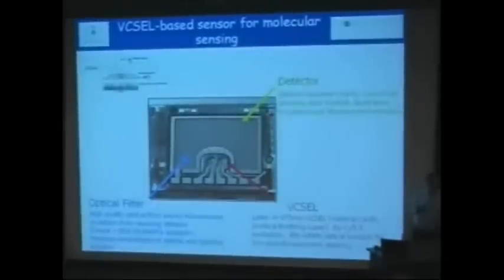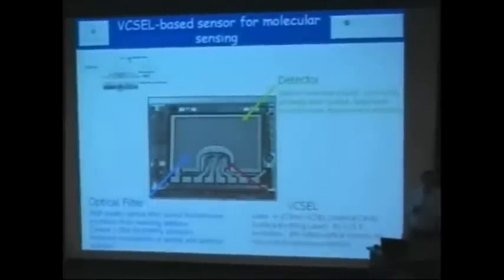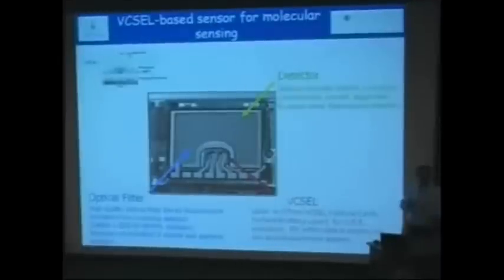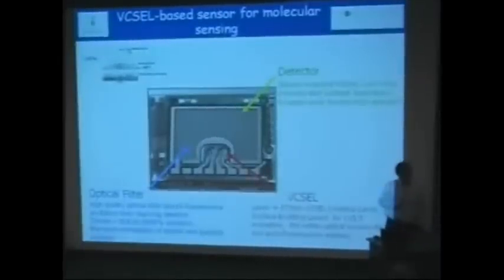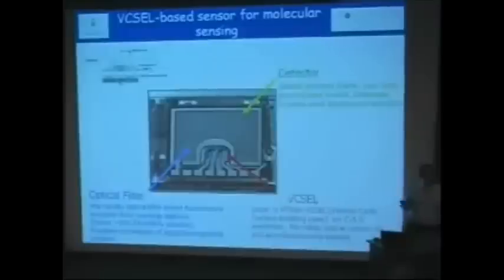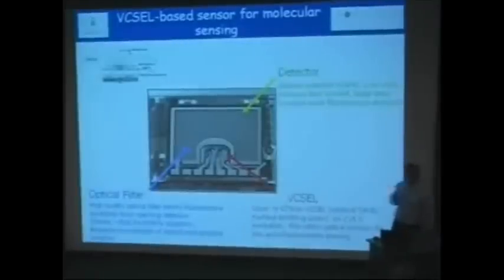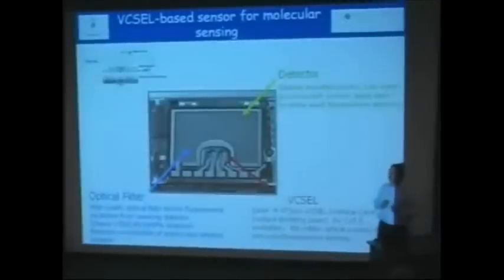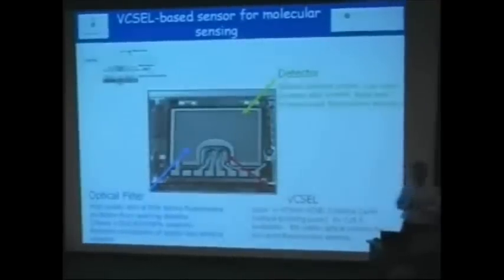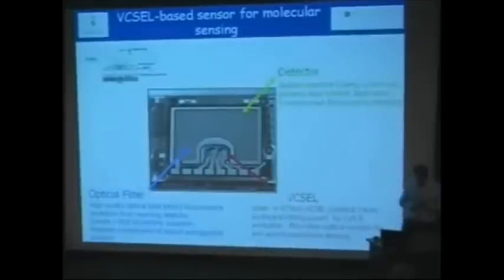For redundancy, we always try to make two and not one, because many times we would burn a laser in the middle of the experiment, and the last thing you want to do is just stop and go home. So we always like to have at least two lasers at the same time. These lasers are at 670 nanometer because this is the wavelength that is optimized for use with the dye we chose. The dye we chose was Cy5.5, which has the advantage of very low autofluorescence in the body as a background. So this is the laser that we chose, and it's shown here in the middle.